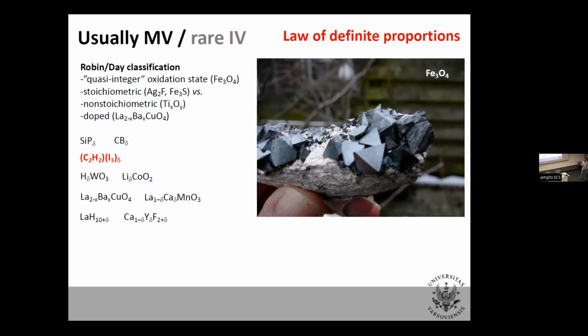So this is a compound from the class, a relatively narrow class, known as intermediate valence compounds. Not the mixed valence, but the intermediate valence. And such compounds, in contrast to the previous group, are usually metallic, so they conduct electricity very well. Why? Because in the solid state you have electronic structure and you've got bands. And if there is some non-integer oxidation state, it means there is some peculiar electronic structure, like in this case, d10 s0.5. And this means, in the first approximation, that the s band is just half filled. And this means a metal. So this is a nice example of an intermediate valence compound.